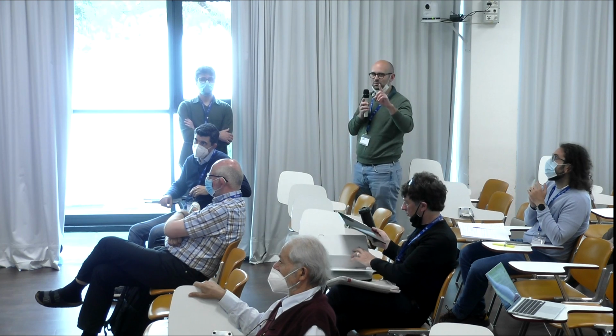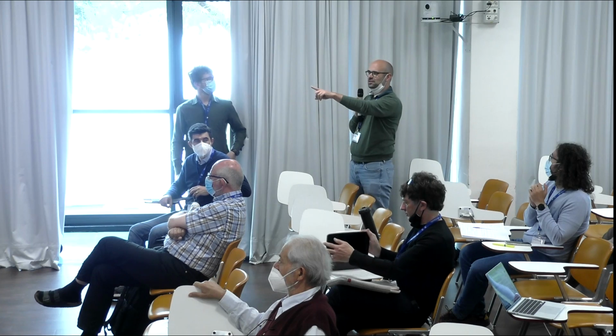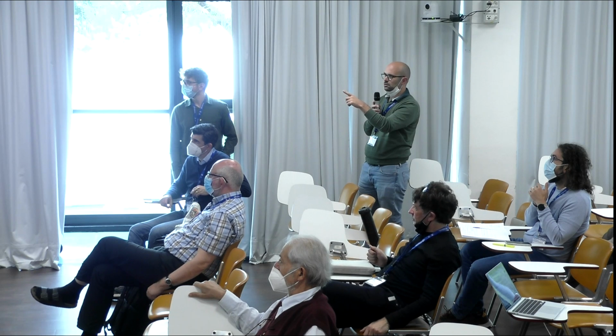Okay. Also, on slide 14, you had this curve where you had a jump at 12, 13 gigapascal. So this was a calculation, right, that had no silicon in it, I guess? Or was it this one, the left one? The next slide. Yeah. This one? Yes, this one. On the left is the calculation, yeah. Okay, because silicon has a phase transition at that pressure from silicon I to silicon II, from diamond cubic to beta tin. So if that pressure is really relevant, can you be sure that your silicon tip is not transforming into beta tin during the experiment?